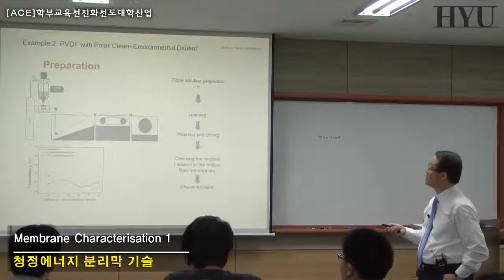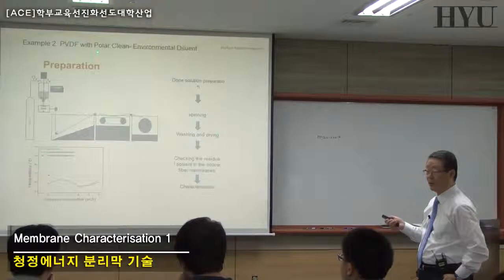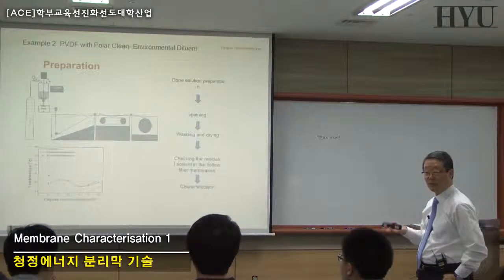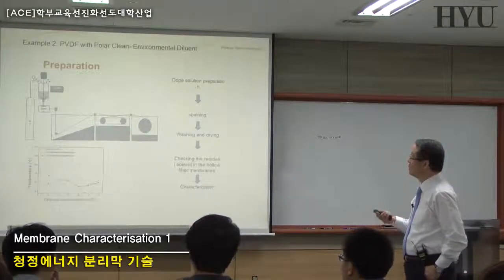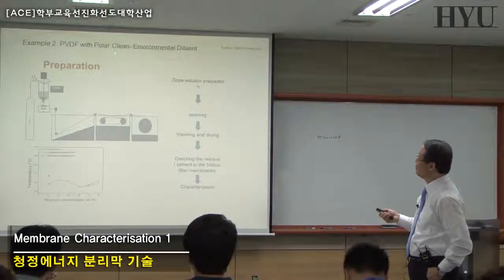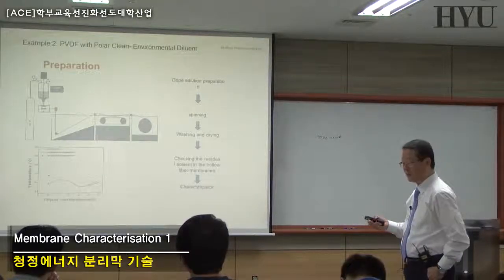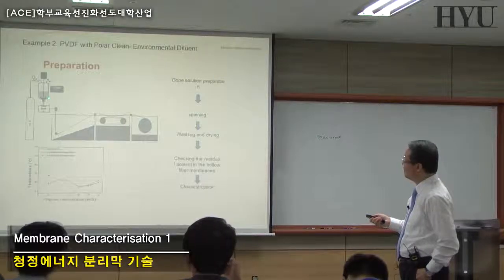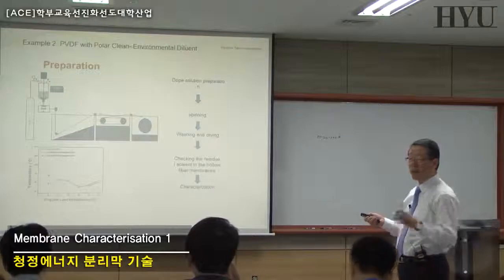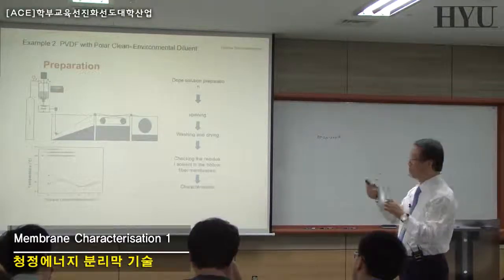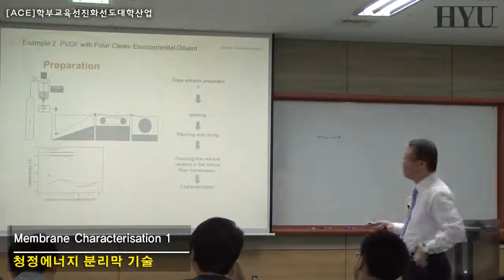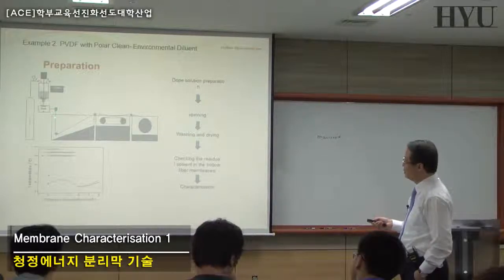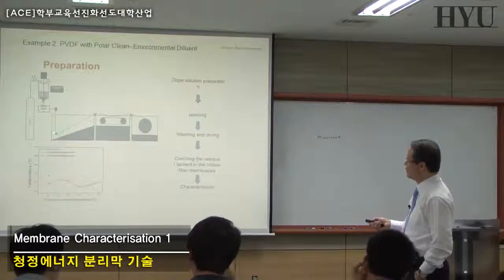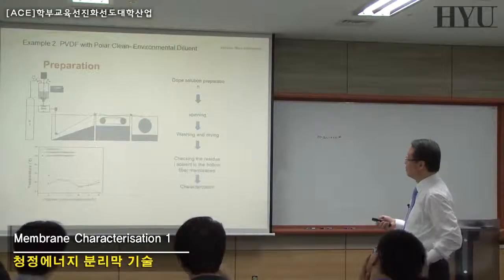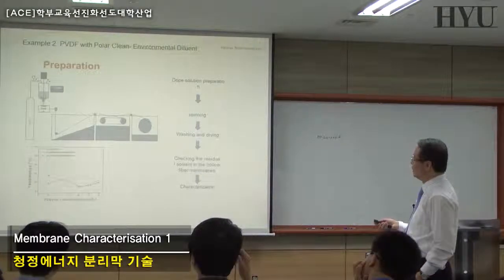Latent solvent, here in this case, is not DOP, but PolarClean. PolarClean is much more environmentally friendly, and much healthier than DOP, so that's why we are using this PolarClean. If we use PolarClean here, we mix this together and increase the temperature to above maybe 180 degrees C, and we prepare the diluents. Diluents could be water or could be PolarClean. So this is regarded as the buffering. And you inject these two into the spinneret and push them into the coagulation bath. By putting this polymer solution into a coagulation bath, you can stretch them to make a much more strengthened fiber, or strong fibers, and make hollow fibers.